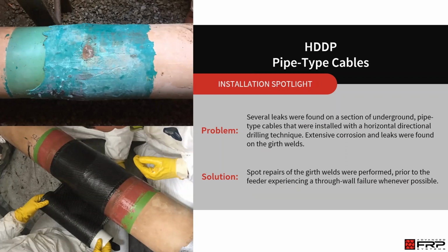Another issue we saw in the field was on something called horizontal directionally drilled piping. Sometimes when you can't dig a big trench in an area for whatever reason, this is another technique where you basically drill or bore a hole in the area and you pull the pipe through. This particular utility had used a traditional girth weld protection system. So, they had thought about the fact that their girth welds could be damaged during this process. Unfortunately, for whatever reason, the system that they chose wasn't up to the task, and they have leaks at several girth welds within their horizontal directionally drilled section of pipe.